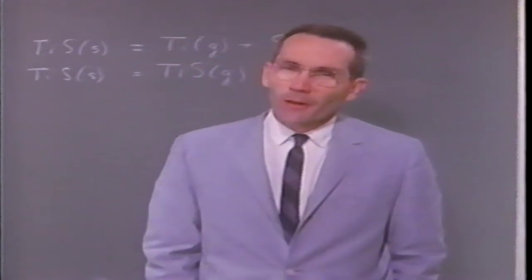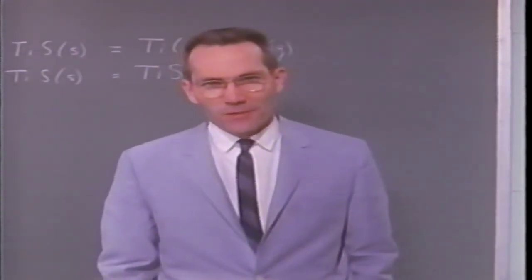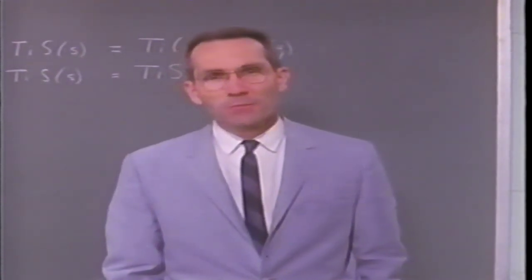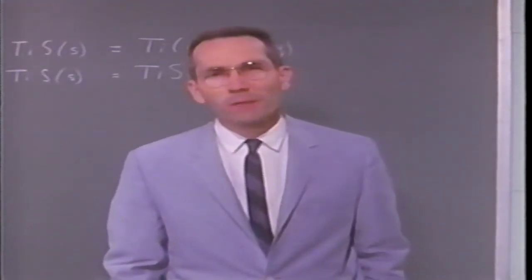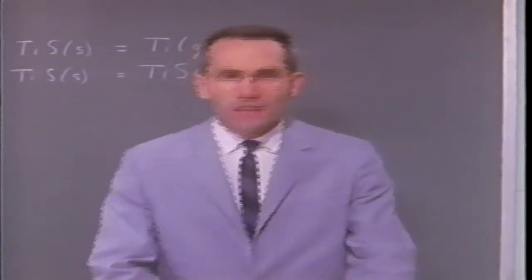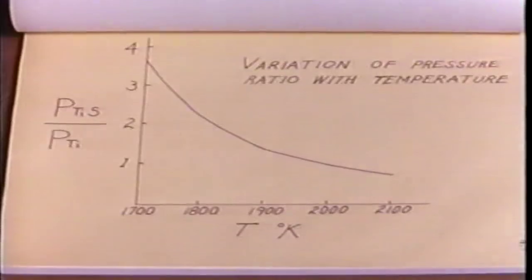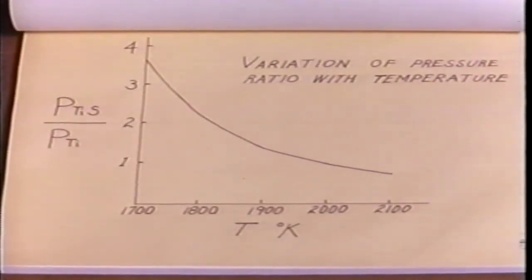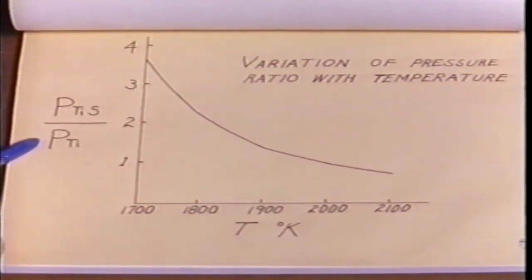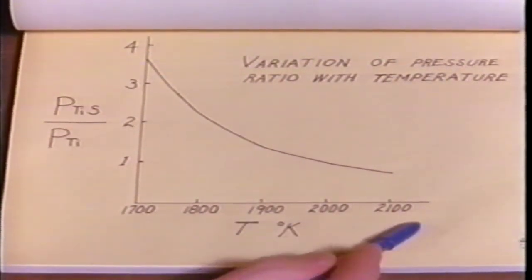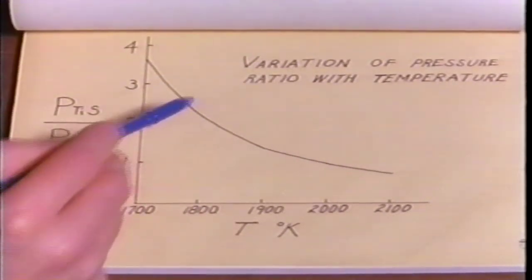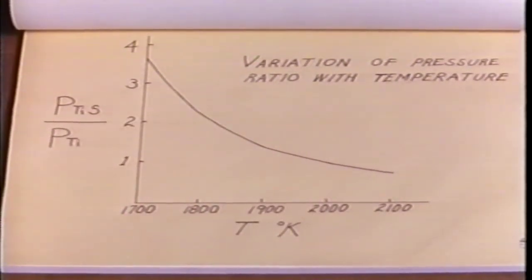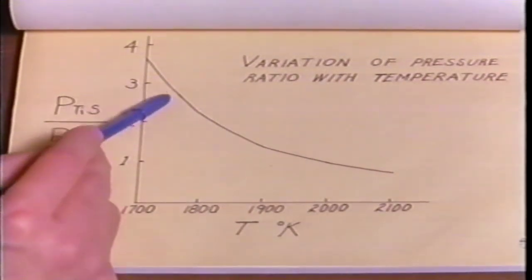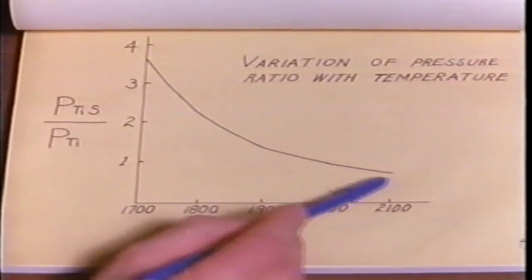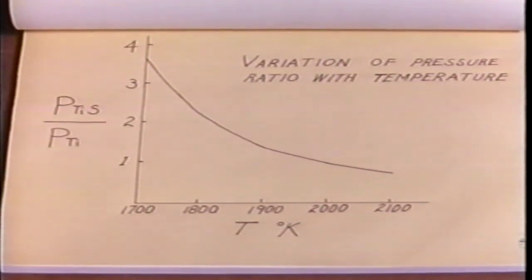Now that we know what happens, we can proceed to measure the bond strength. To do that, we make measurements at different temperatures. Now, what would you expect would happen? Well, here are the results. We have used the mass spectrometer measurements and have plotted the ratio of the pressure of TiS to that of Ti as a function of temperature. Here is the 2.1 to 1 value at 1805 degrees Kelvin. As you can tell, the proportion of TiS in the vapor decreases with increasing temperature.